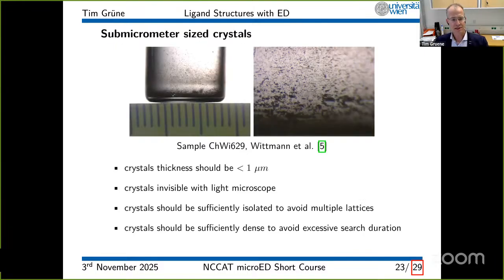This is a sample from Christopher Wittmann. You see this is a glass vial. It's about 1.5 centimeters wide, half of an inch. And this is the powder that we had inside. So obviously these crystals are way too small for X-ray diffraction. The crystals are tiny. But we can still see the grains under the light microscope. This is a picture recorded with our light microscope. So any grain that you can make out here would still be too big for electron diffraction, and we have to make them even smaller.